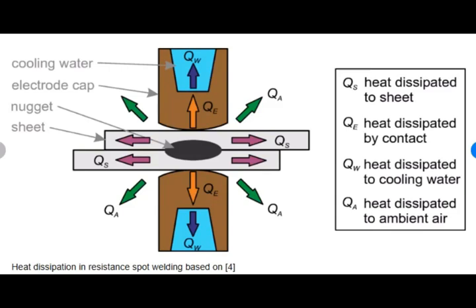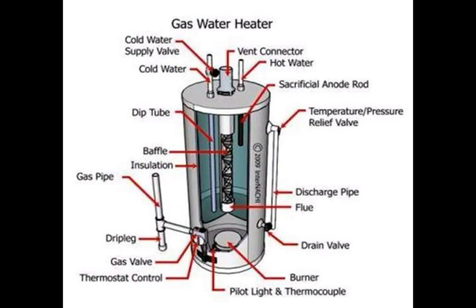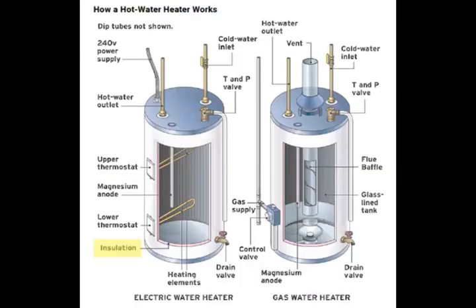In this diagram, the heat generated at the faying surface leaks through several different paths. The majority of the heat leaks through the top and bottom sheets to the water-cooled electrodes. The leak to the ambient is very small, we don't have to worry about it. The leak to the metal sheet horizontally is the reason we need a transition ring to insulate the weld and metal sheets. Just like a water heater, we need an insulation layer to insulate the heater core from the outside. This way the heat from the hot water will not leak to the ambient.